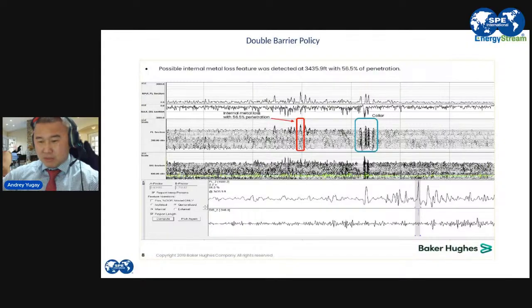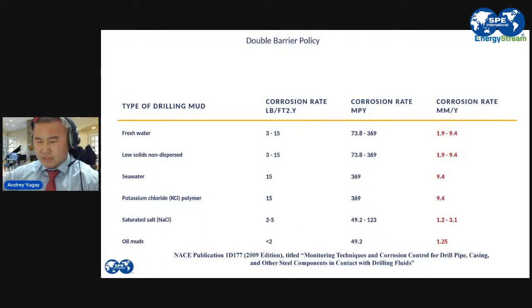Because what happened in this particular workover, drilling team, they were so scared, that they almost do not have a barrier in place. So the well was plugged and abandoned straight away. Now, how we can control the corrosion of the secondary barrier? From outside, we can use coating. Yes, from inside, we need not to expose to the corrosive environment.